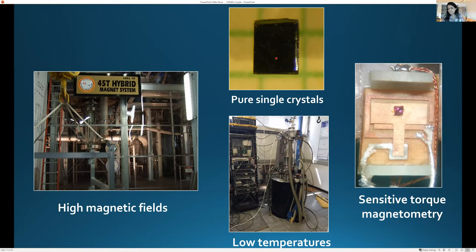So this is an example of a crystal mounted on a beryllium copper cantilever. So this is flexible. And the plate you see below is fixed. So the magnetization of the material gives you a certain torque when a magnetic field is applied. And as the magnetization changes, M cross H changes, the magnetic torque changes. And so this upper flexible cantilever deflects, and the separation between the base plate and the flexible plate changes. And if we measure the capacitance, so these are coax cables going off to measure the capacitance. So the separation between these two plates changes. And we're talking about very, very small amounts and deflections of like fractions of a radian.